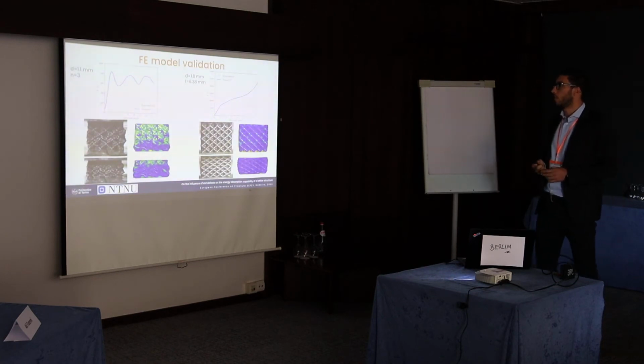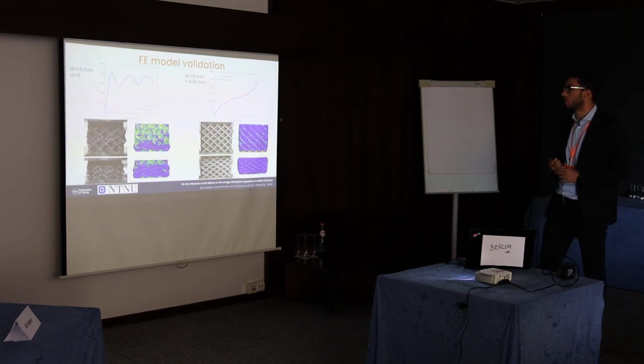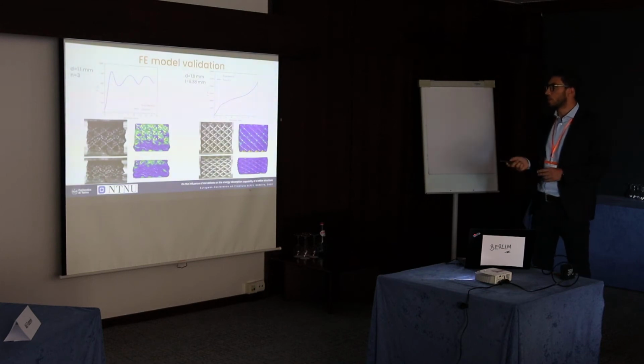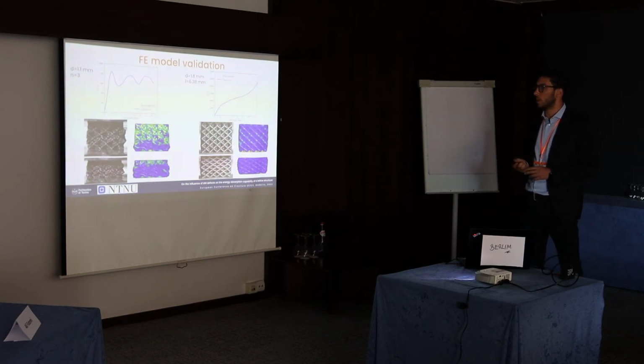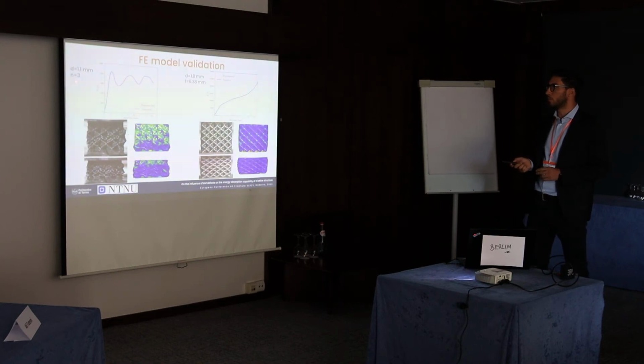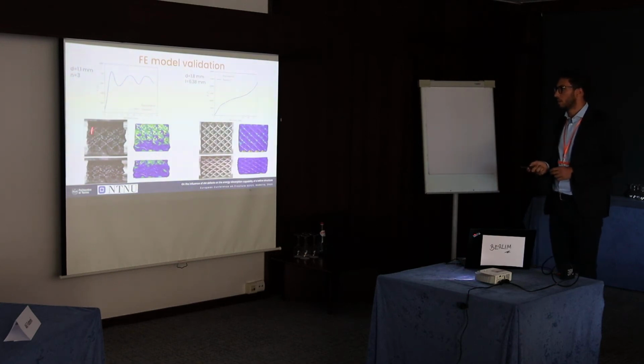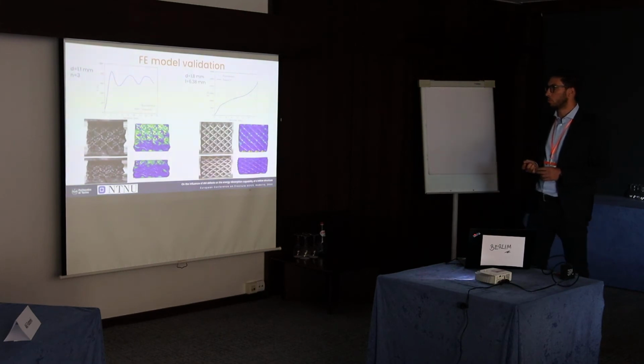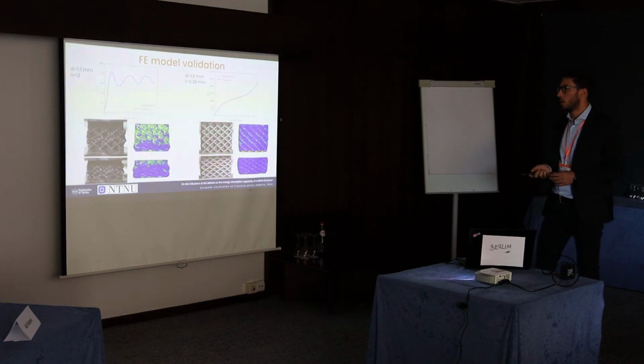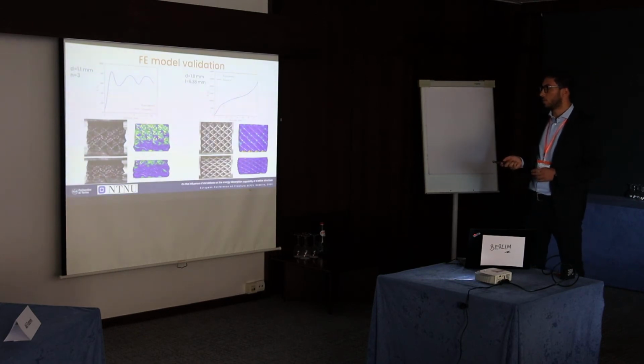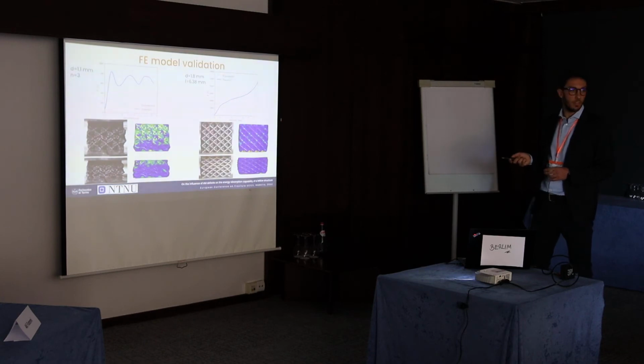So here is the validation of the finite element model. I'm sorry that the green line here is not very visible. Anyway, this is the comparison between the two. Here on the left we have a case of the second factorial plan with the diameter of 1.1 millimeter and 3 replications of the cell. And you can see that the finite element model is able to capture the progressive crushing behavior of this structure, which also results in a force displacement curve that is characterized by these peaks and valleys. And these are mainly due to the fact that each layer of cells progressively crushes.